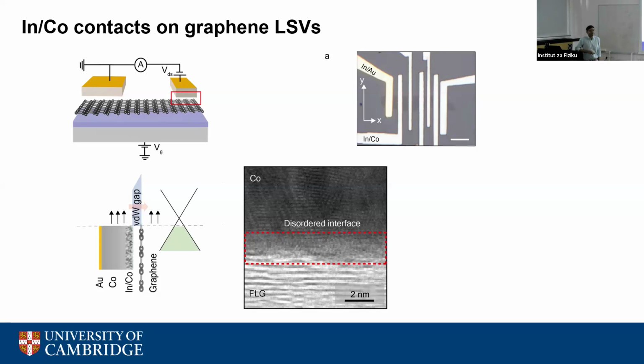I mean, nothing can be 100% clean, right? But for these devices we use PMMA, which reasonably gets you very clean surfaces if you can develop them cleanly after the lithography process. I think if you have more residues at the interface, they would act as nucleation sites, and that would give rise to the 3D growth which I was talking about. So the deposition has to take place in ultra-high vacuum, and to answer your question, we do not use any additional step to further purify. We just use standard development procedures and ensure that the evaporation takes place in ultra-high vacuum.